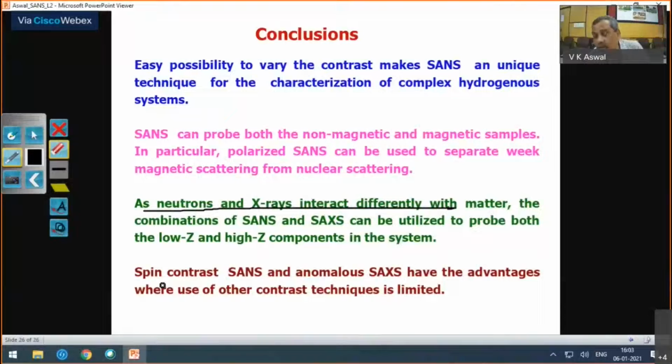And today he talked about contrast, where I will especially request you to pay attention to how you can make part of a large particle visible or invisible by matching the contrast between H2O and D2O. You know, in neutron interaction, H has a different scattering length compared to deuterium. The chemistry remains the same, but the contrast is so good that you can mix D2O and H2O literally in a beaker and make different parts of a particular particle visible or invisible. And the same thing goes for when you do a spin variation, you could see that. Any other questions?